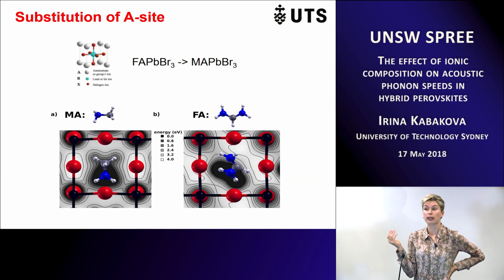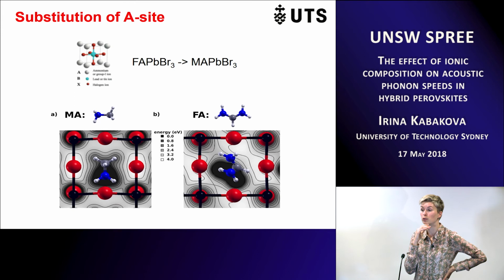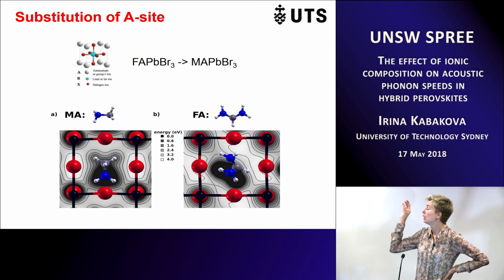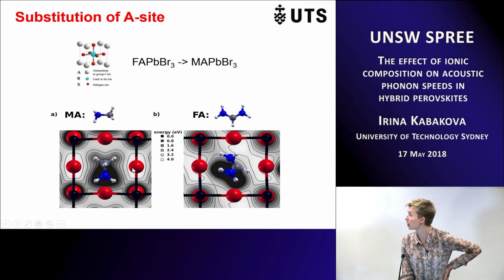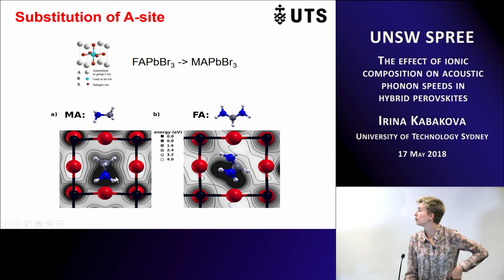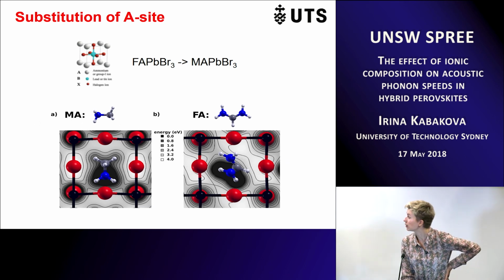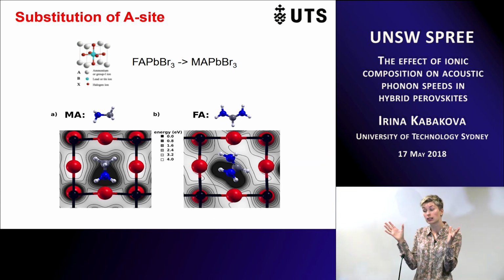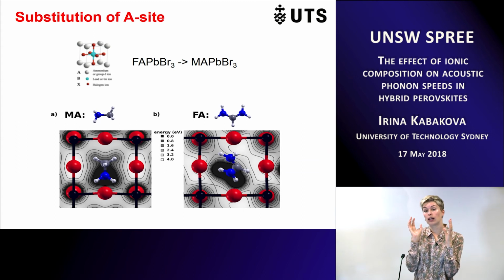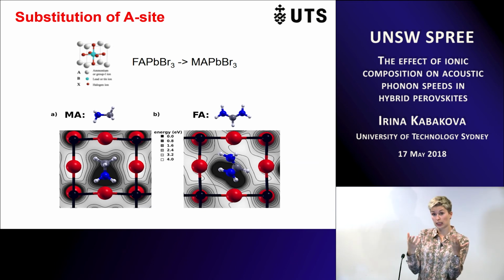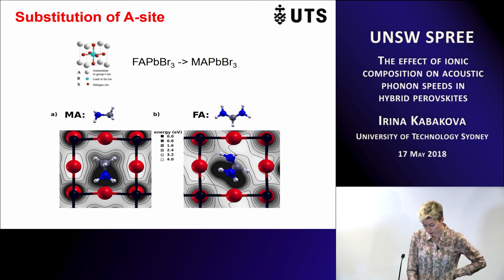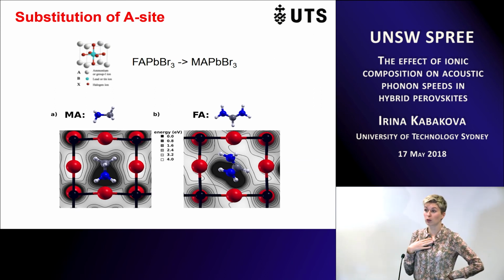If this explanation makes sense to you, good, but I'm happy to take it to discussion after I finish the talk. Essentially, the symmetry of potential energy, and the fact that the potential energy gradient around the organic molecule methylammonium is more compact and interacts less with the lattice, means that electrostatically it's a stronger configuration, and so it happens it also has a higher elastic constant, higher acoustic speed, and it's more stable and stiffer. We didn't expect this at all, and it doesn't come from just analysis of the two